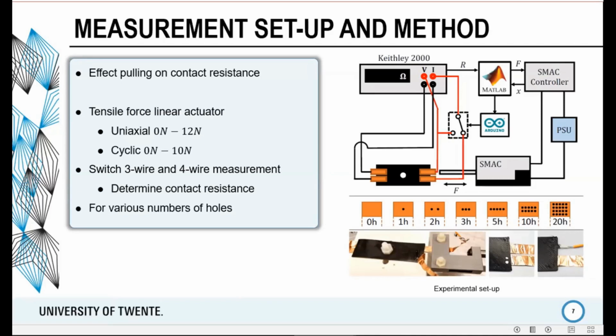And we did this for various numbers of holes to see what the effect is of changing the hole pattern or changing the number of holes, where we clamp one of the contacts and pull on it, and then we had samples with copper tape and with wire connections.